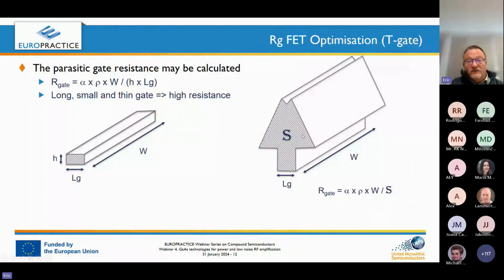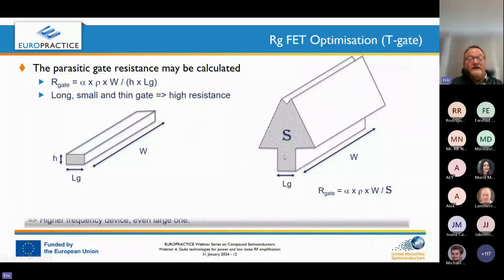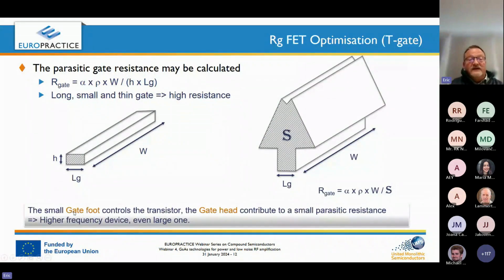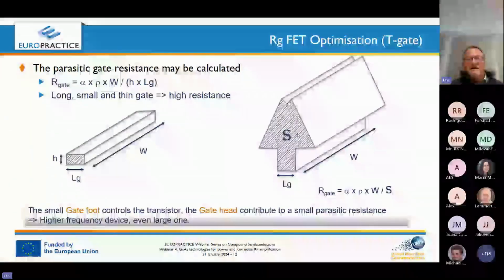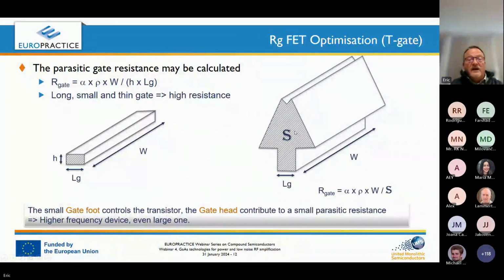With this trick, the gate resistance is again proportional to the length of the device, but divided by this global surface, which means we can go higher and higher in frequencies. We still have the gate foot, which is very small to control high electron velocity, but we have a gate head, which is big and which significantly reduces the resistance, leading to a very high cutoff frequency. So we can keep high frequency on the device, even a large device, for our applications.